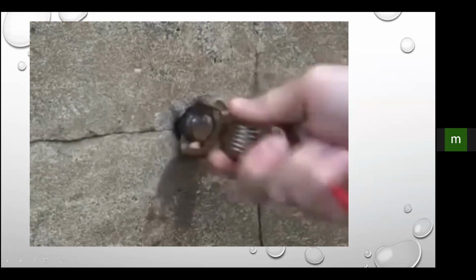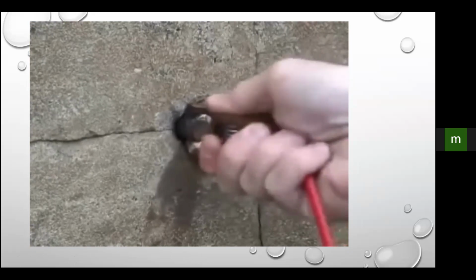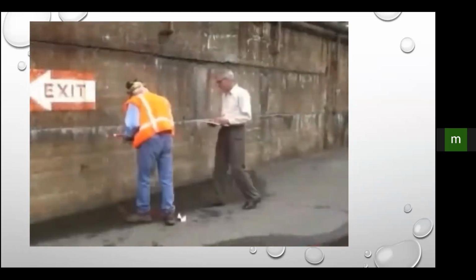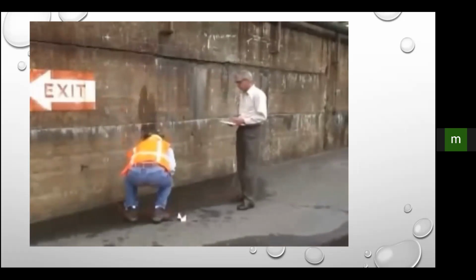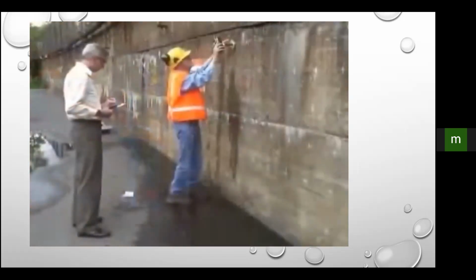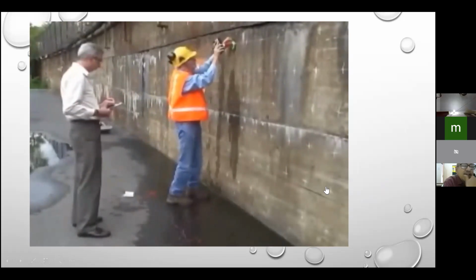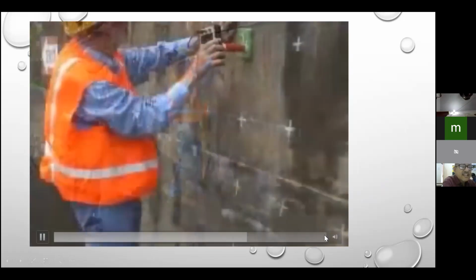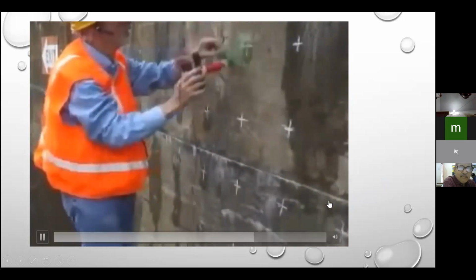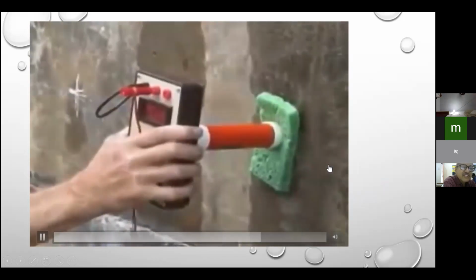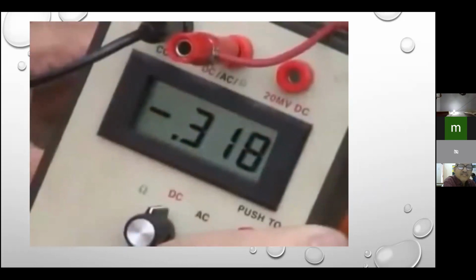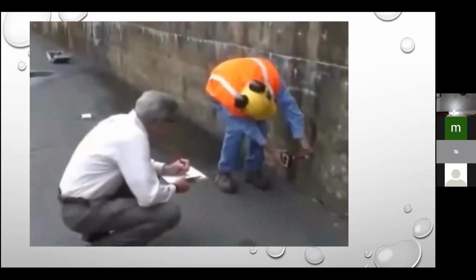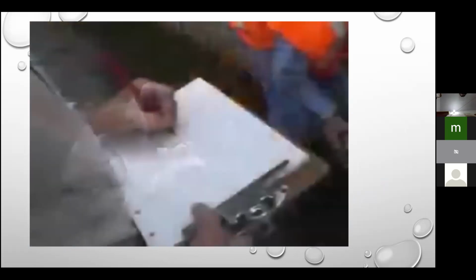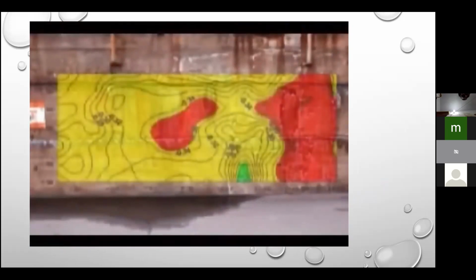The red positive lead from the voltmeter is then clamped onto the bar. Prior to measurements, a grid is laid out with 1-foot spacing spanning across the concrete surface to be tested. A wet sponge is placed between the porous plug of the half cell and the concrete wall to complete the circuit. Potential measurements are taken at each intersection along the grid. The measurements and their corresponding locations are recorded, and this data is used to generate a contour map of potential corrosive sites beneath the concrete surface.